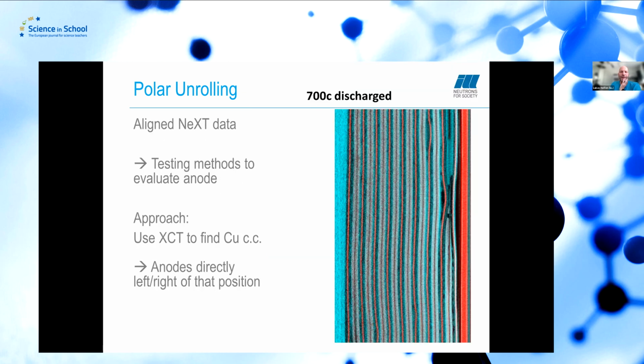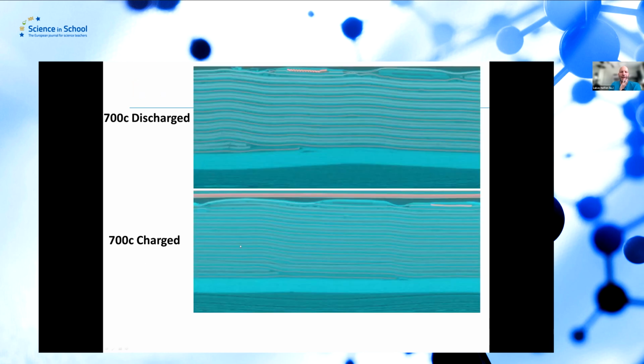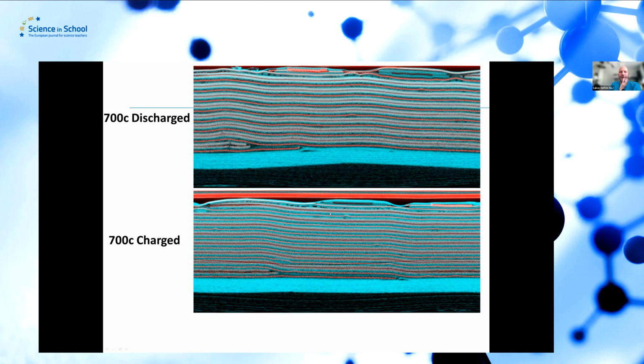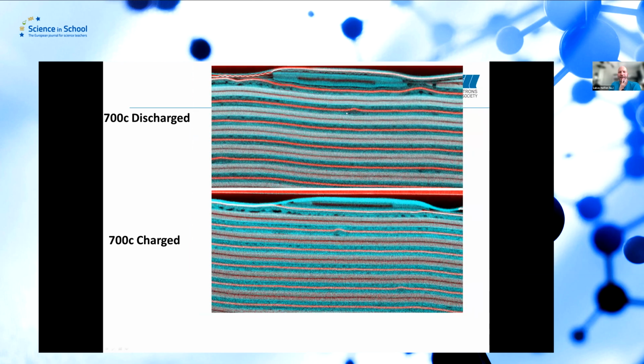for the discharge state here, for instance, after 700 discharging charging cycles. And you can do the same thing for the charged one, which is here in the bottom, with the contrast increased. And if you zoom in on some interesting regions, we see that there's a lot of variation. And this variation is due to the discharging cycle. So the material ages, and the lithium is trapped here in the discharge state in the anode material, for instance. And we get also voids or weakly lithiated regions, both in the anode and in the cathode material in the charge state.